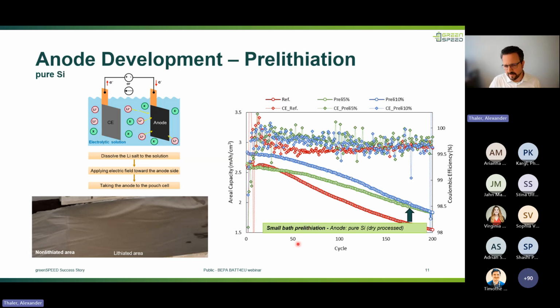development. What might be important to say is that the pure silicon anode was not processed on the roll-to-roll. It was actually done with a bath pre-lithiation, but the results are obvious that it is important to investigate the pre-lithiation degree, and how that is then behaving in the final cell. Okay,